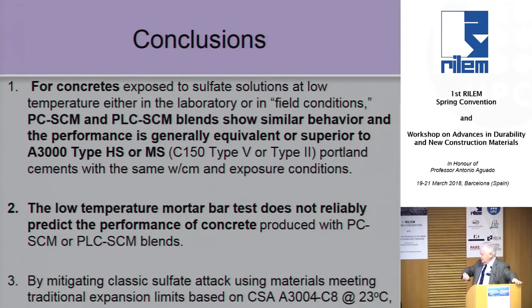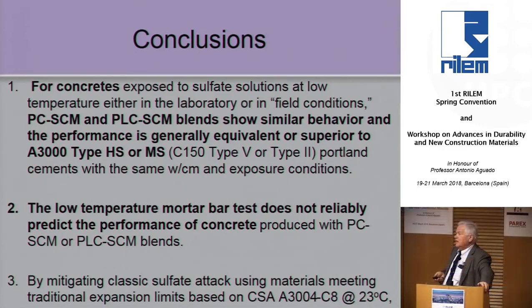Okay. So not wishing to go too far, I just want to conclude by this, that the concrete exposed to sulfates at either cold temperatures or mixed temperatures, where they're going up into cycling temperatures between 3 and 15 degrees Celsius, showed that if you have sufficient mitigation with supplementary materials or using blended cements, that we got equivalent or superior performance to sulfate-resistant systems that are currently used, and that the mortar bar test that we'd originally developed wasn't very reliable in predicting the concrete performance.